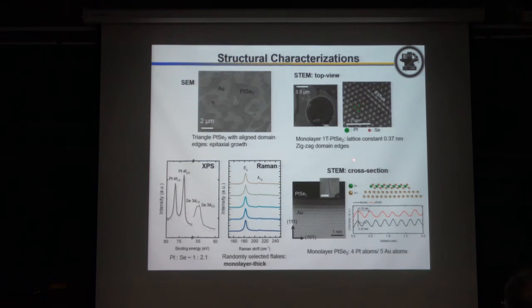So we have some characterizations, using SEM and also atomic resolution STEM. You can see PtSe2 is the 1T phase, and the lattice constant is about 0.37 nanometers. And we also show from cross-section STEM, you can see very clear PtSe2 layer and gold. And they also have some alignment. For example, 4 platinum atoms aligned with 5 gold atoms. So this is a kind of commensurate stacking.